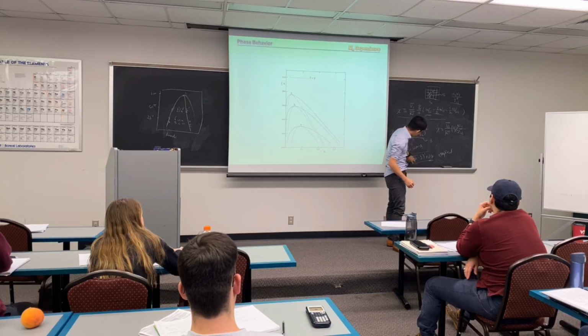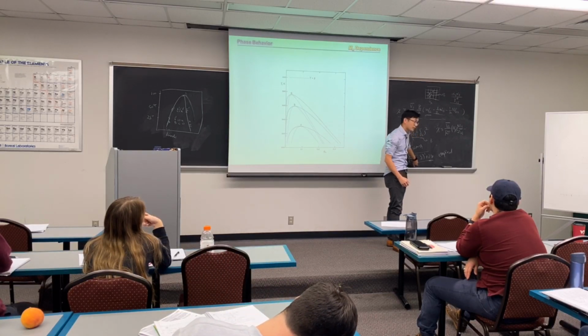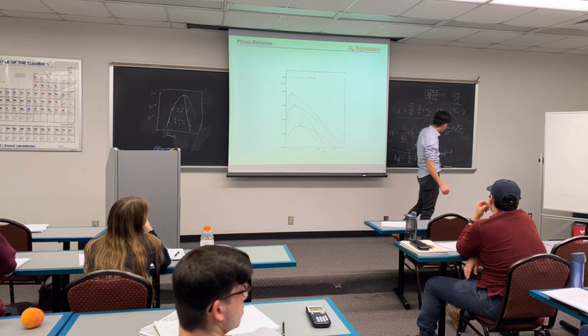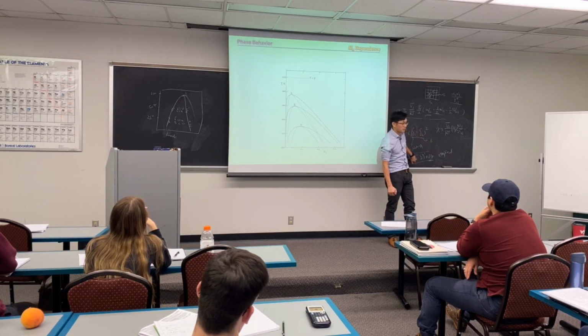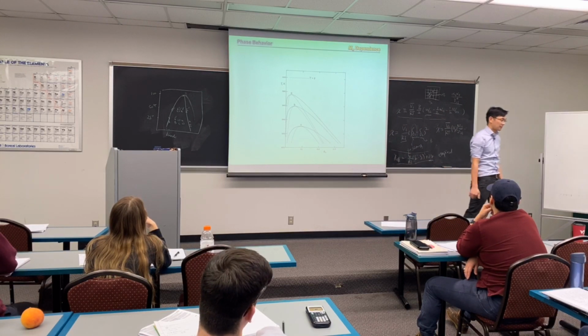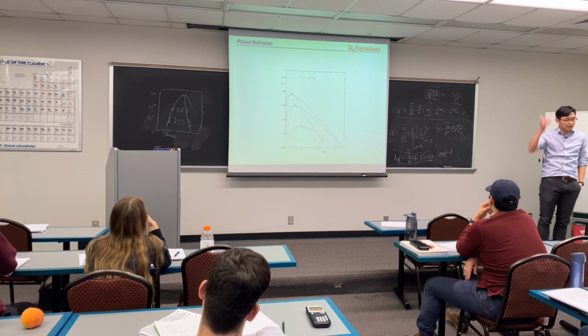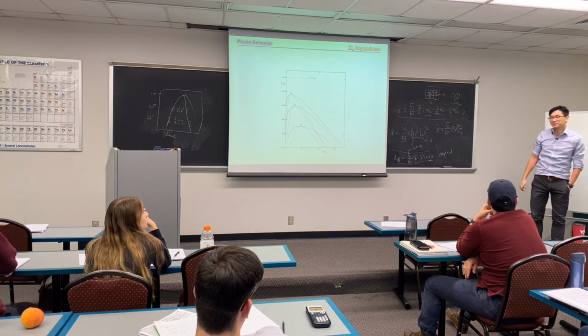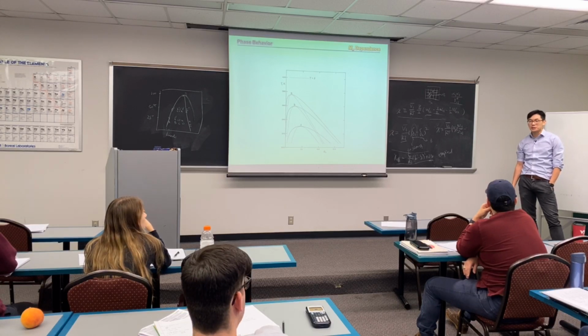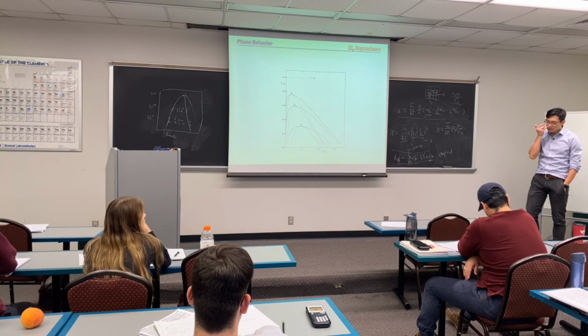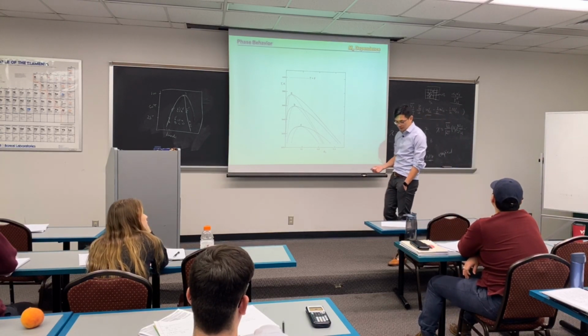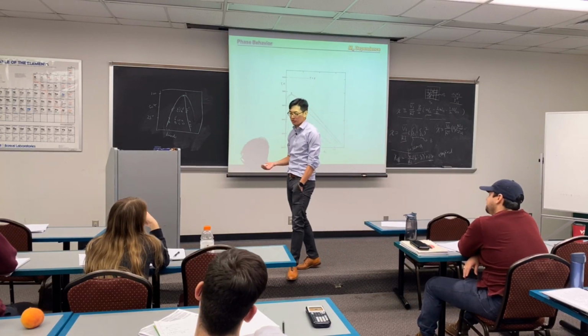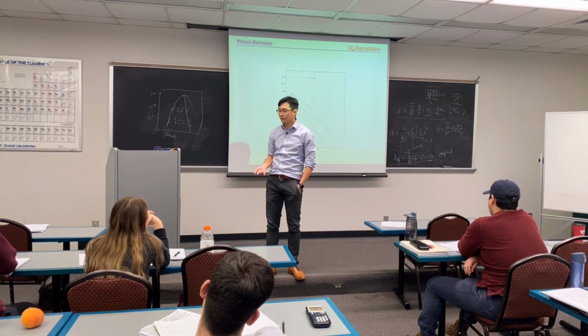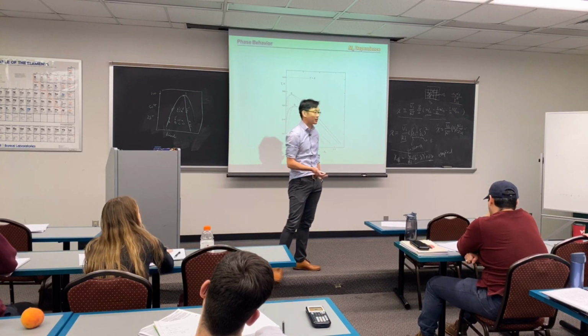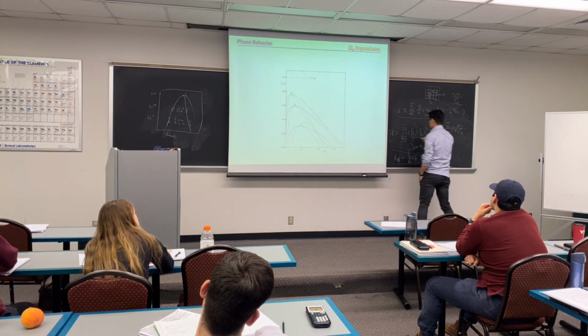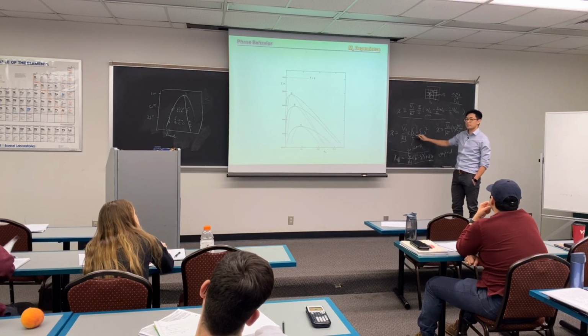Those are usually just constant, but what really changes your effective chi parameter is the solubility parameter, this delta 1, or the cohesive energy density, which is the square of the solubility parameter. So at the end of the day, when I look at the phase diagram of a polymer and solvent, what I really need to do is basically have a polymer handbook in hand. I need to know the chi parameter. Then I can eyeball what will be the entropy contribution and what will be the enthalpy contribution, right? And as we mentioned, chi is always going to be larger than 0, because these two terms are always going to be positive. Solubility parameter 1 minus 2, squared.